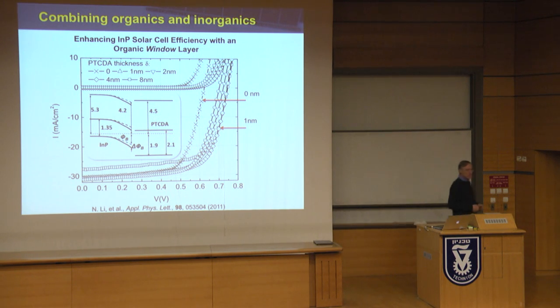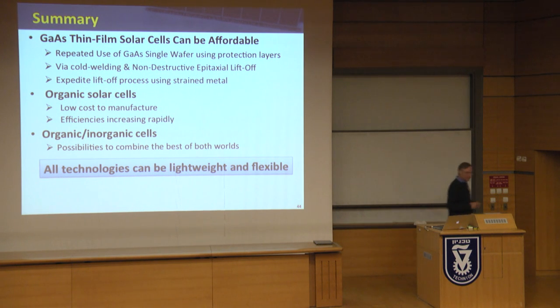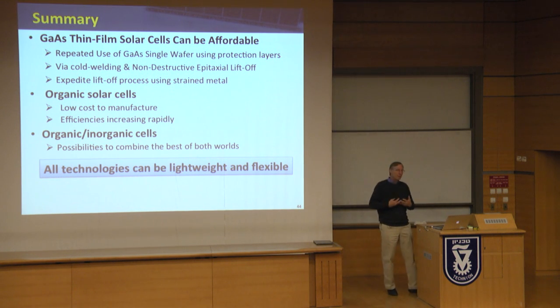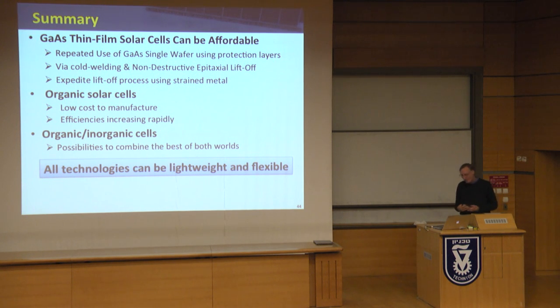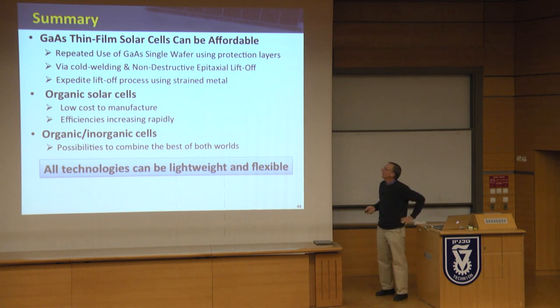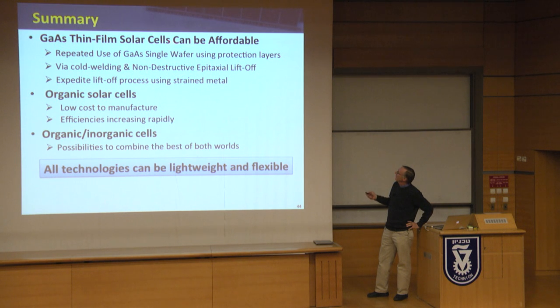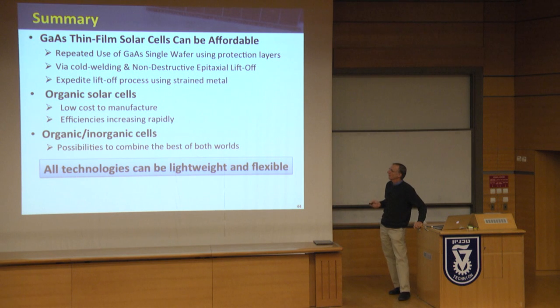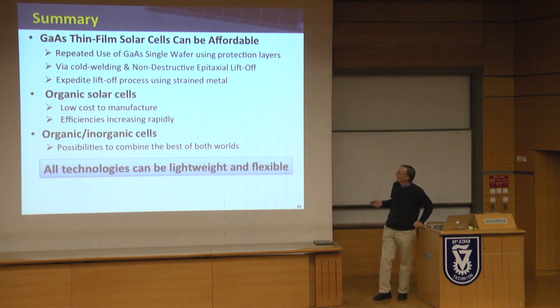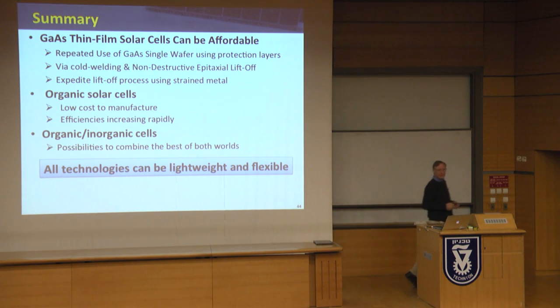So this is one way we can use organics. The other thing is you can actually harvest sunlight with those things too and drive those excitons to this interface, and we have recently managed to do that as well. So it's kind of a fast excursion through two technologies, but in our mind they're serving the same purpose, which is to deliver high efficiency and lightweight and deployability for power generation. The gallium arsenide thin film solar cells can be affordable. We absolutely are confident that that's true, but we need to use this non-destructive epitaxial liftoff. Organic solar cells are very low cost, low energy to manufacture. Efficiencies are zooming up. And possibilities to combine the best of both worlds may be very speculative in that one, in organic, inorganic cells. All of these technologies can be lightweight and flexible, which is definitely a different way to be looking at solar cells today.